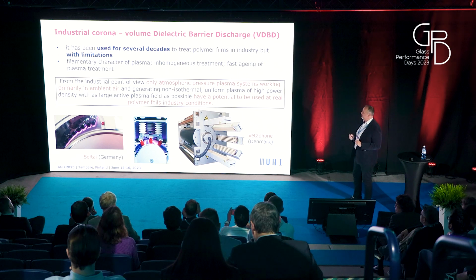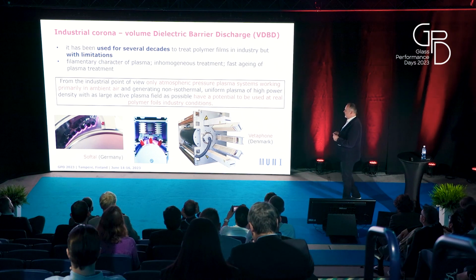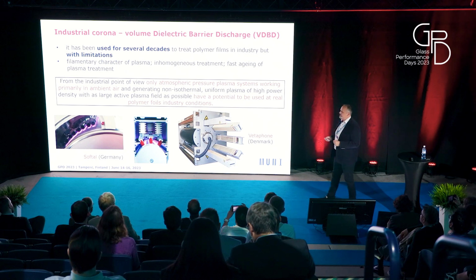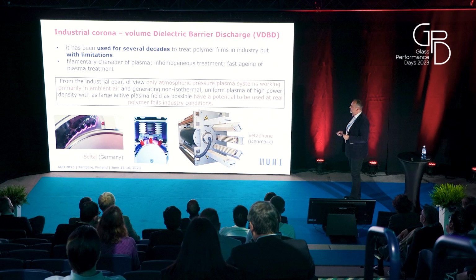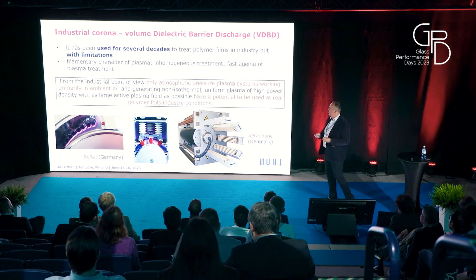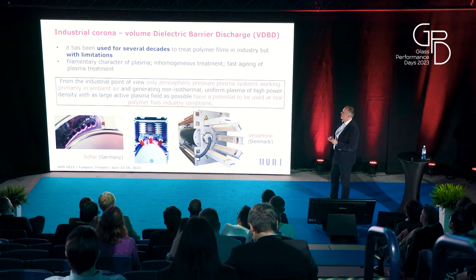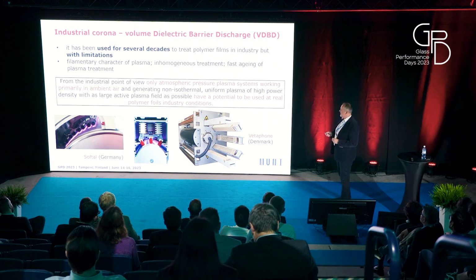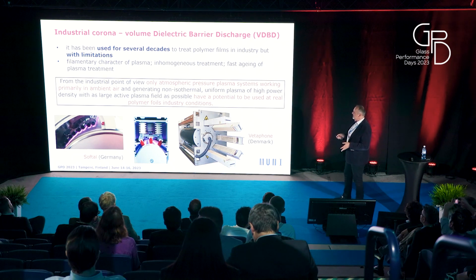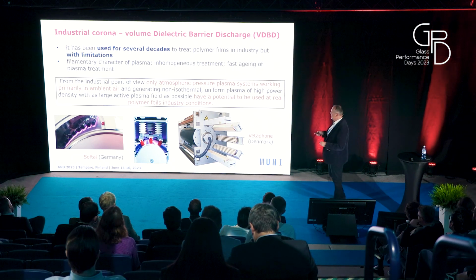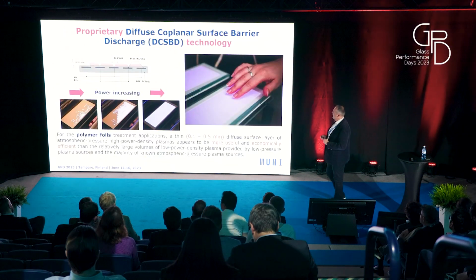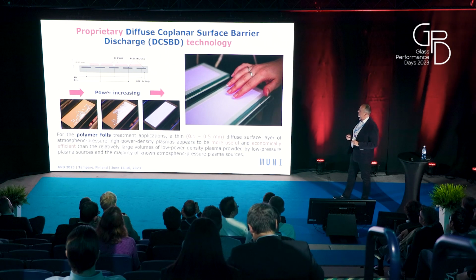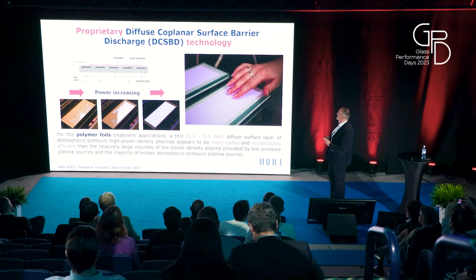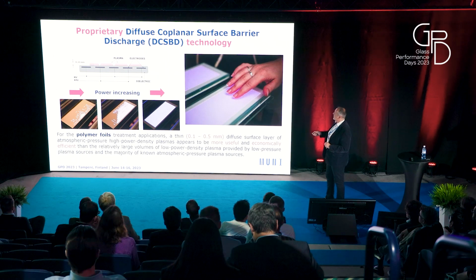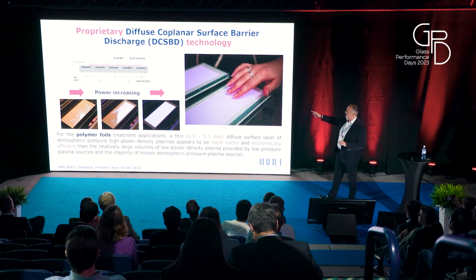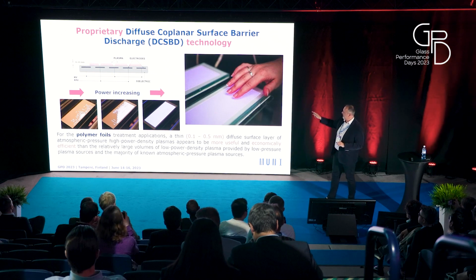For treatment of polymer films and also maybe PVB or ionoplast, we can consider standard volume DBD discharge, which has been used for decades for the treatment of films, and it is also called industrial corona in technical literature. But this discharge has several disadvantages, like stability of the treatment, limited thickness of the material, and so on. So I would like to introduce our own technology, which is based on the so-called diffuse coplanar surface barrier discharge. And as you can see, we are able to generate macroscopically homogeneous plasma without any stabilization by flowing gas.